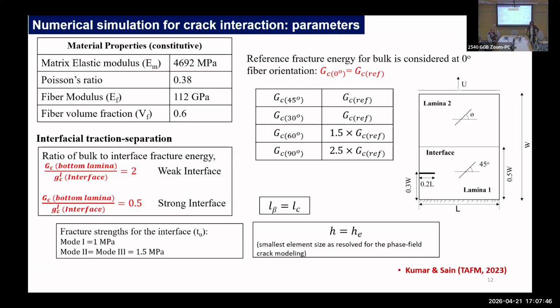Sorry. Go ahead. So you use a smoothing method to smooth the crack itself and also the interface between the different layers or lamina of the composite. Could you use that sort of method to apply it to the discontinuities between the fiber and the matrix? I assume there is some sort of discontinuity. Yes, because the material properties are so distinctly different. Yes, you can do that, but imagine that around each fiber, if you define the interface, it will be computationally expensive to capture that. But in theory, it can be possible. And we did some simulations.